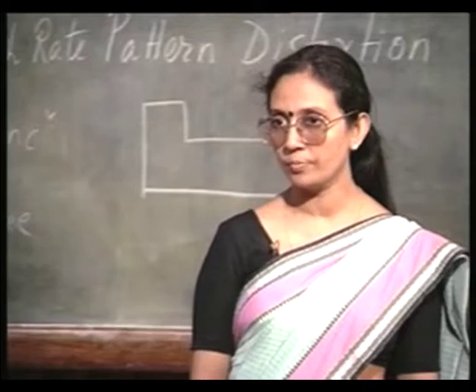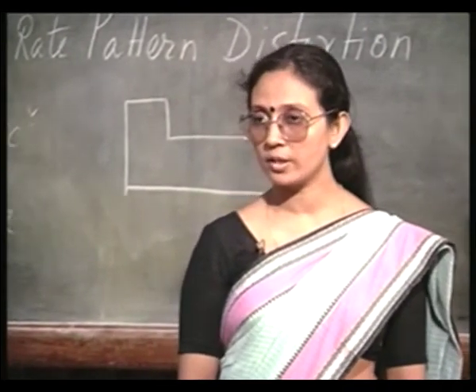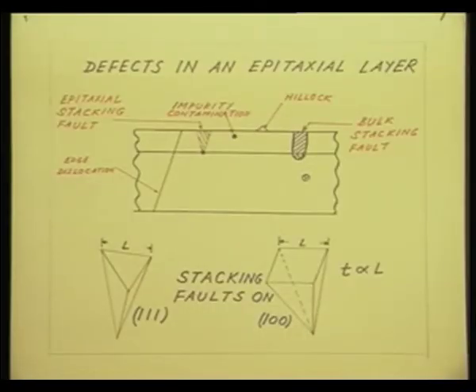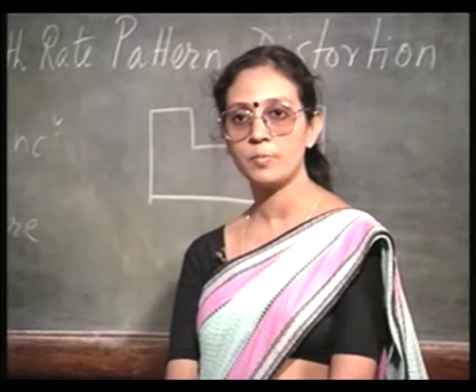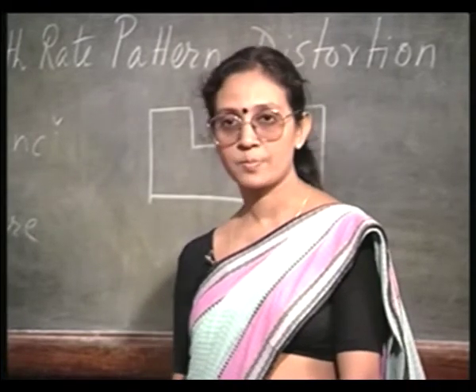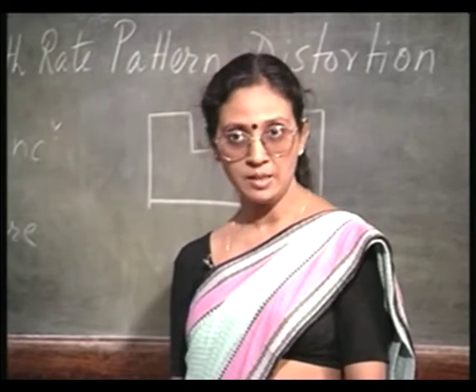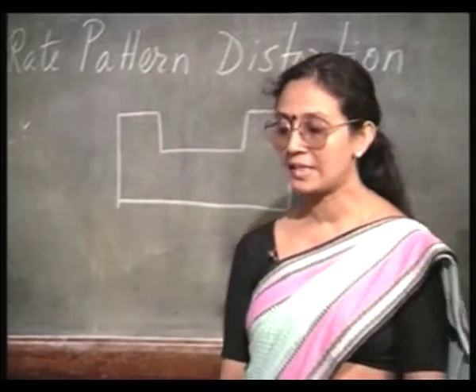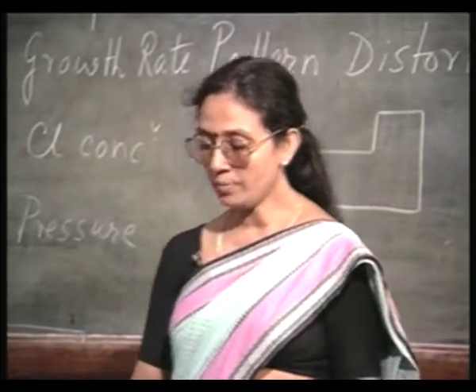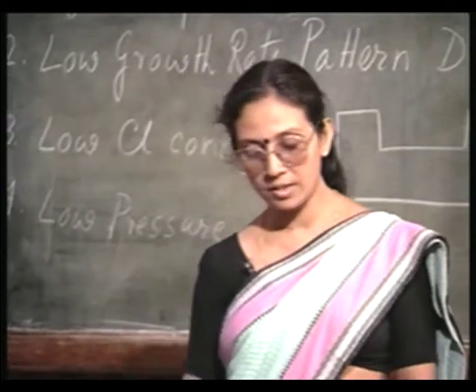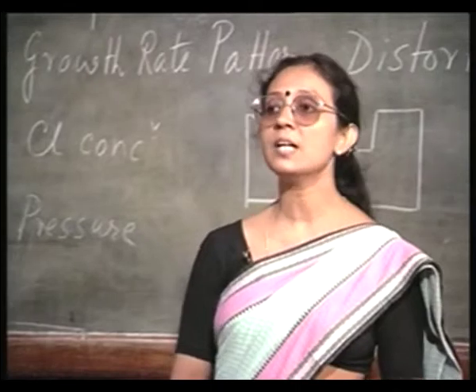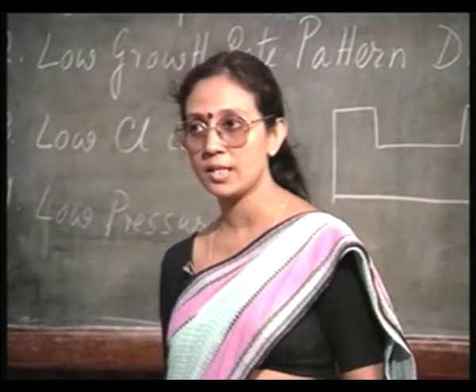You know why this is so. The answer lies in the crystal orientation itself, right. On 1 1 1, what I find is an equilateral triangle. Each side of the triangle is actually in the 1 1 0 direction, and on the 1 0 0 surface what I find is a square or a rectangle, again with each side in the 1 1 0 mutually perpendicular direction, okay, and exposing the 1 1 1 faces in the bulk, right. That is what this signifies. As I told you, the most important reason for these stacking faults is the presence of small patches of native oxide on the surface.